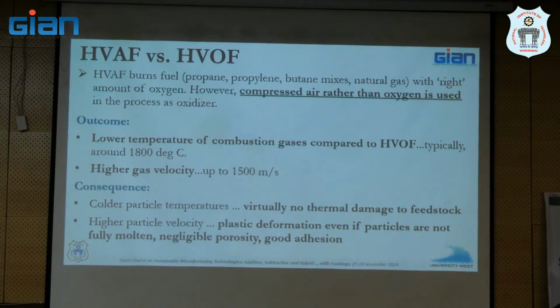So that's a big advancement. I spoke about it a little bit, but very quickly, let's compare HVAF, which is new, with high velocity oxy-fuel, which is old, right? And see what the differences are. The main difference is that you use compressed air instead of oxygen. We also spoke about what that leads to. It leads to much higher gas velocity because you are using 5 times as much gas as you would if you used oxygen, and therefore it lowers the flame temperature.